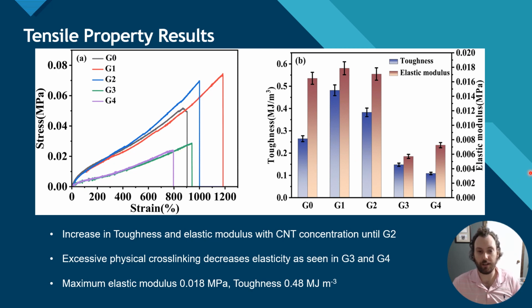The first property we decided to test was the tensile properties. This was done using a universal material tester at room temperature. We took each sample from G0 to G4 and tested their stress strain at break, calculated their toughness and elastic modulus. What you'll notice here is that an increase in carbon nanotube weight percentage yielded an increase of toughness and elastic modulus up until the G2 sample. At this point, the physical cross-linking of the carbon nanotubes reaches a point that decreases the plasticity of the polymer and can be demonstrated in a reduction in the elastic modulus and toughness here in the G3 and G4 samples. Our largest toughness and elastic modulus can be noticed here on G1.